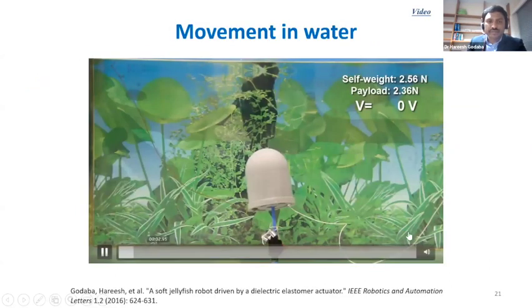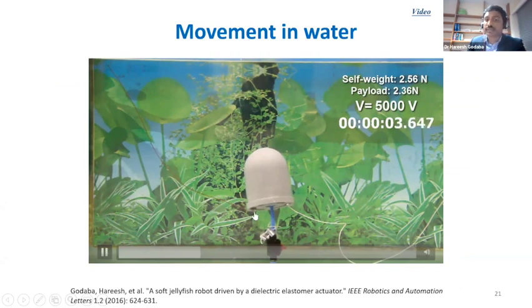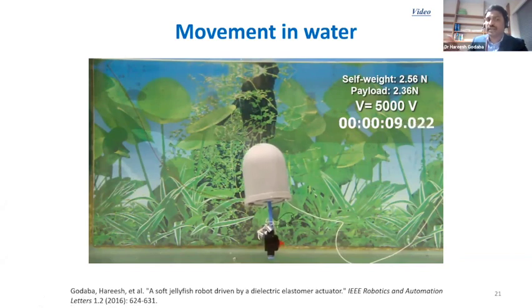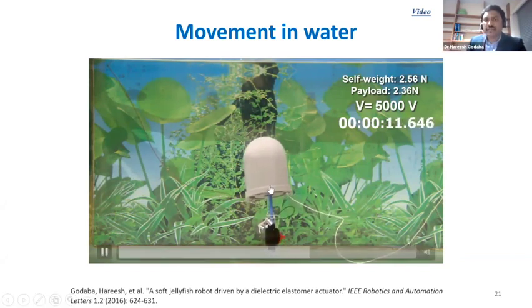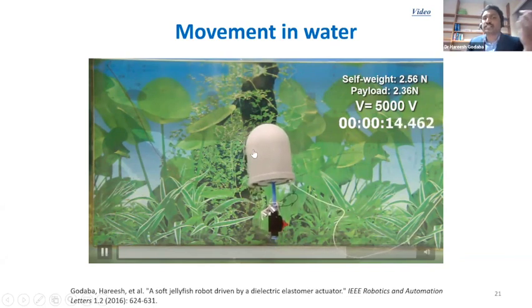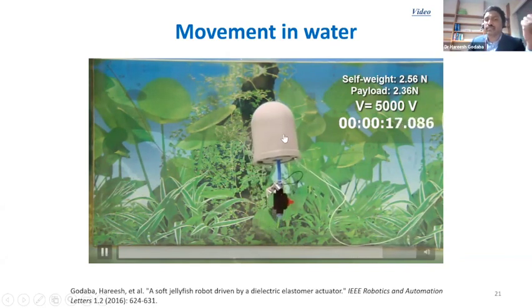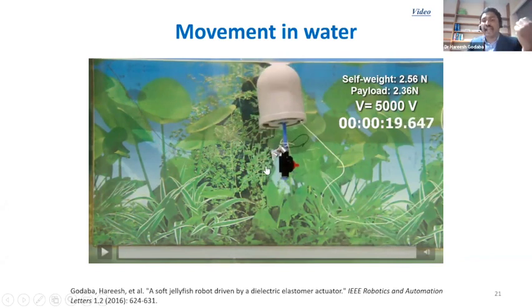And then we tested this underwater, and you will see that at the start there is a sudden jerk, which is created due to the thrust force generated by suddenly actuating the membrane. After that, when the voltage is constant, there is a constant buoyant force acting on the chamber that can make this robot move up in water. And we see that we can have a payload of 2.36 Newton for this type of setup.